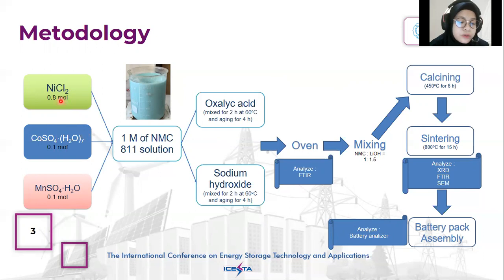The research methodology was to prepare nickel, which is obtained from nickel chloride, cobalt, obtained from cobalt sulfate, and manganese, obtained from manganese sulfate, with the ratio 0.8 mol, 0.1 mol, and 0.1 mol. After that, all these materials were dissolved with distilled water to produce a 1 molar NMC 811 solution. We can see on the slide that the result of dissolving is a bright blue solution. The color of the solution indicates that it contains nickel, manganese, and cobalt.